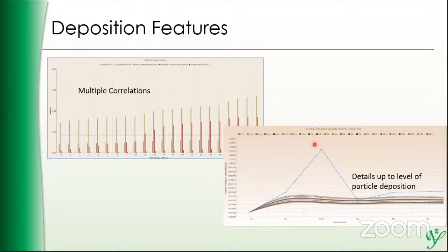Again, then we have the deposition graph. So here you can see the critical transport velocity versus the liquid rate. What we do is we calculate the critical transport velocity given the input parameters for each and every particle which is defined in the PSD. Like Joe and Babu sir told you, there are finer particles, which for example here, these are 2 micron, 3 micron, 4 micron, going to 45 microns, and even going up to 500 micron particles. So the PSD which has been entered for this graph is from 2 microns to 500 microns. And for each and every particle, we have calculated the critical transport velocity, which are depicted by these colored curves.